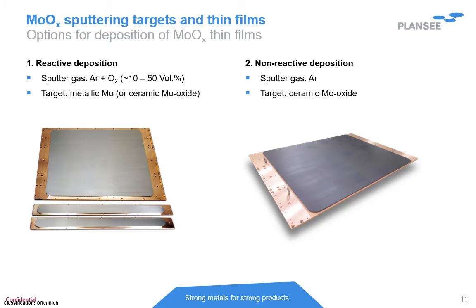Another option is non-reactive deposition. Here you have the advantage that you do not have to add oxygen in the sputtering gas, but you have to use a ceramic molybdenum oxide. Those molybdenum oxide targets are currently available in different compositions with different oxygen contents.